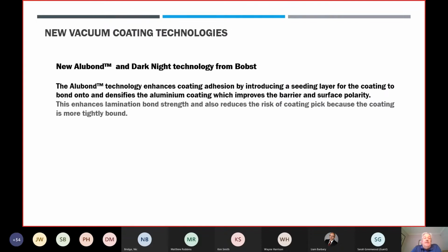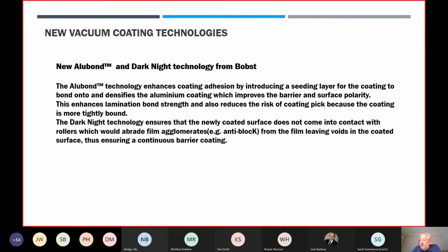So we have new vacuum coating technologies, and I'd just like to thank Nick Copeland for having a discussion with him recently about their new Alubond and Dark Night technology. Basically, the Alubond enhances coating adhesion, and it does that by introducing a seeding layer for the coating to bond onto. And very important, it densifies the aluminium coating. And that means that the aluminium atoms are more closely packed, and so there are less interstitial spaces between them. And so there's less room for vapors, whether it be water or oxygen, to pass through.